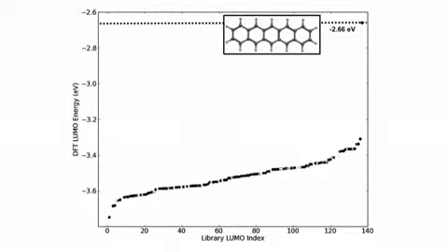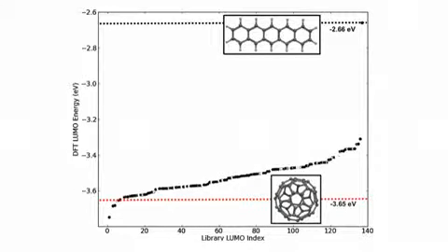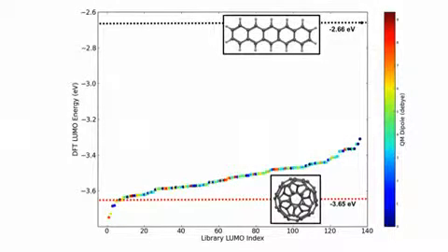Compared with pentacene, all candidates have lower LUMO energies and are all within the range for efficient charge separation. Indeed, the LUMO energies are in a range that is comparable to C60, indicating their suitability as potential candidates for electron acceptors. Coloring the points by dipole moment provides a useful indicator for the charge transport efficiency, as a sizable dipole moment can impede electron transport.